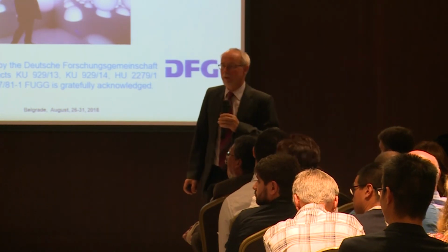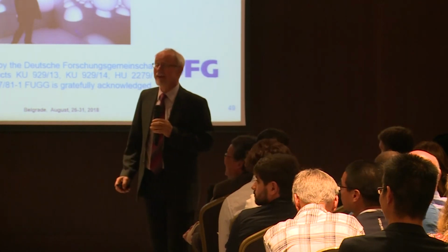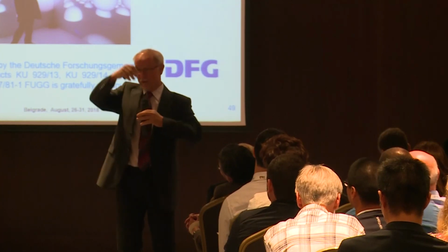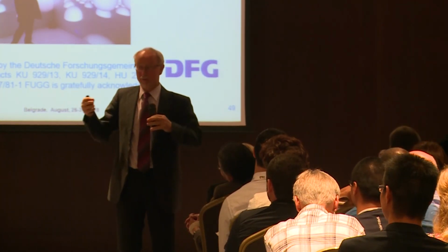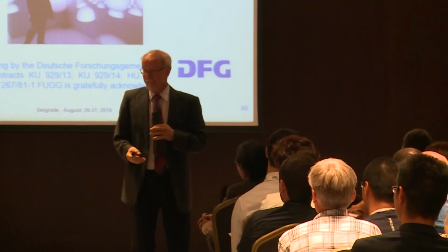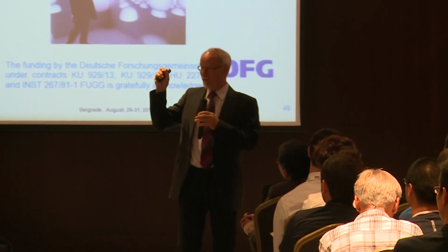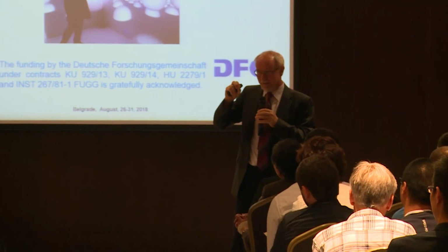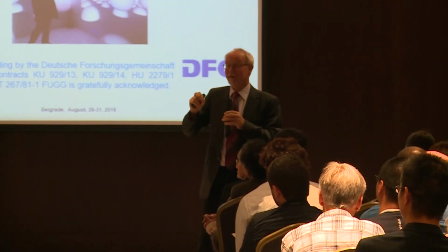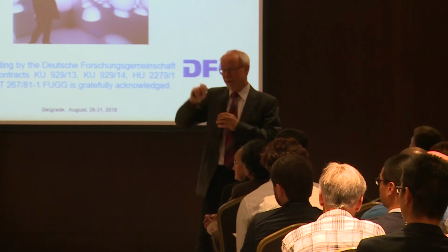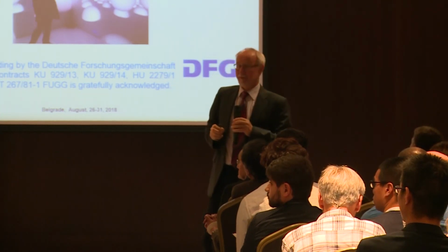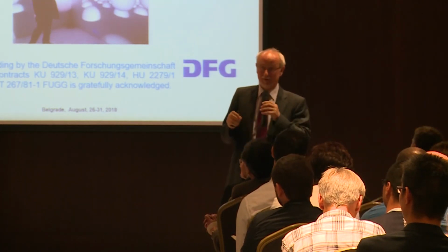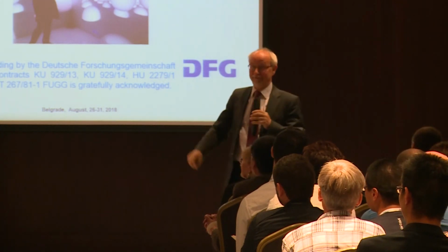I don't think so, because it depends on the size relation. If the process zone encompasses many voids, many grains, then it doesn't matter. If it is very tiny, if it has only one deciding localized site very close to the crack, then you are right. Then all depends on the geometrical statistics and material behavior. But that's not the case, which also shows in all the fracture toughness experiments. They find some distribution function.